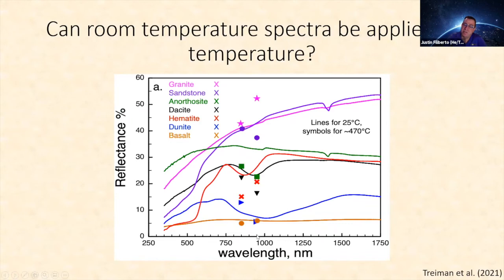And you can see our measurements were done at 900 nanometers, or 0.9 microns, and just below that. So we're just below that 1 micron feature that we can see on Venus. And importantly, at least at first order, and with the exception of hematite, we are getting a good match. There are some differences, but we are getting a good match.